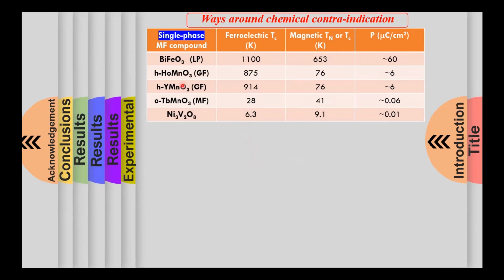In another class of multiferroics, like the hexagonal rare earth manganites, like the holmium and yttrium manganites, the source of ferroelectricity is basically the buckling of the rare earth oxygen plane and tilting of the otherwise rigid manganese oxide bipyramid. This mechanism of ferroelectricity is called geometric ferroelectricity.